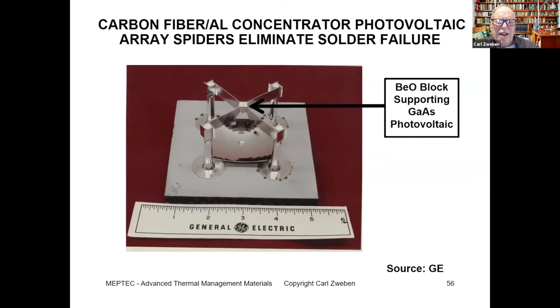This is one of the most interesting applications that I've ever been involved in. This was a photovoltaic array for a spacecraft. It was an experimental array. And the idea was that the incoming solar energy is reflected off a mirror and onto a high efficiency gallium arsenide photovoltaic cell. And to dissipate the waste heat, the gallium arsenide photovoltaic cell was mounted in a beryllium oxide block. And the next problem was getting the heat out of the beryllium oxide block.